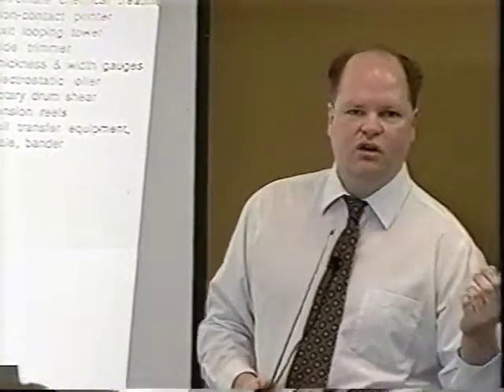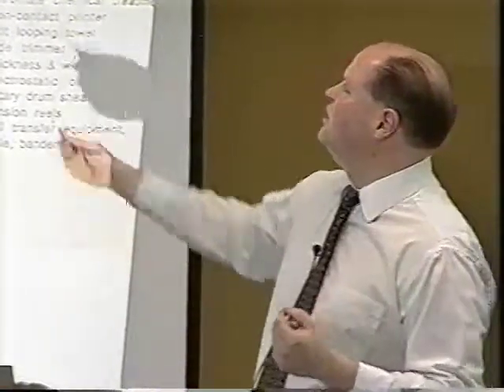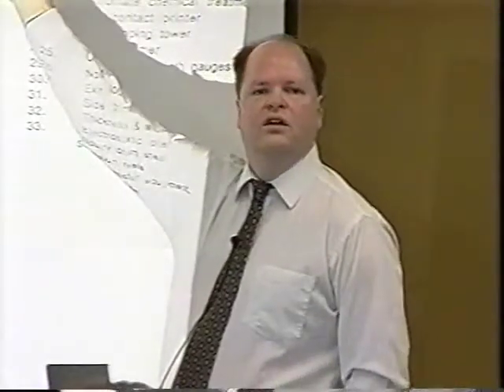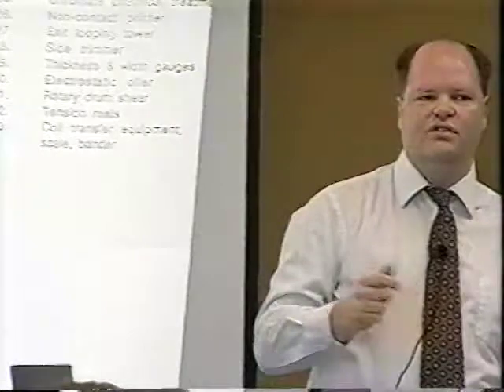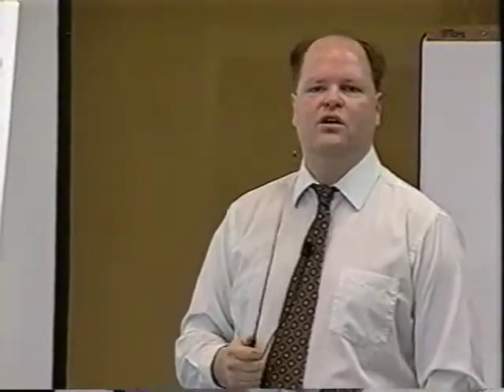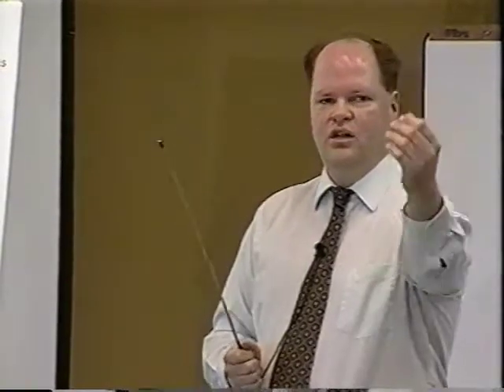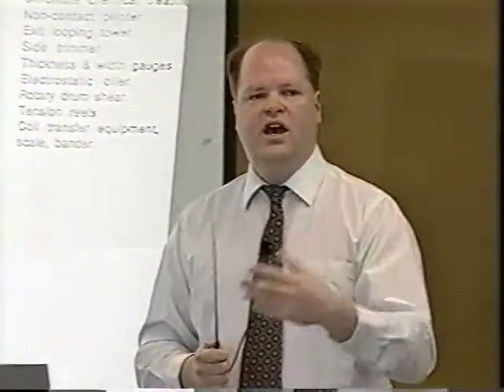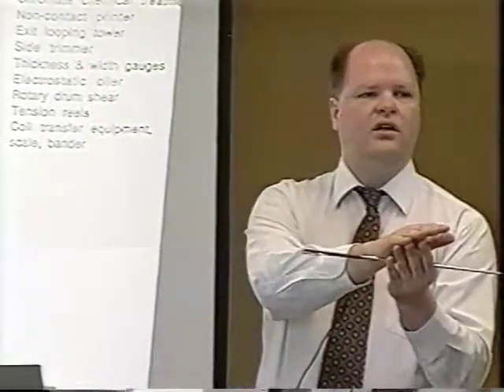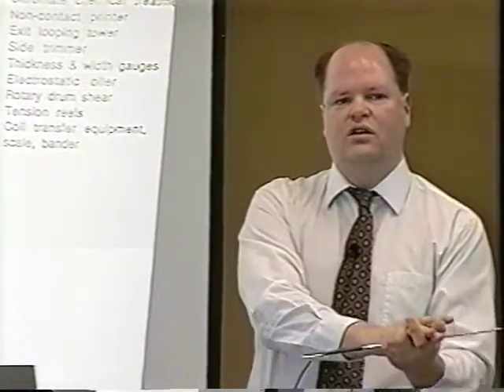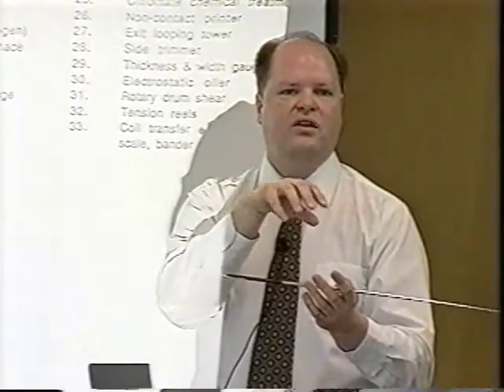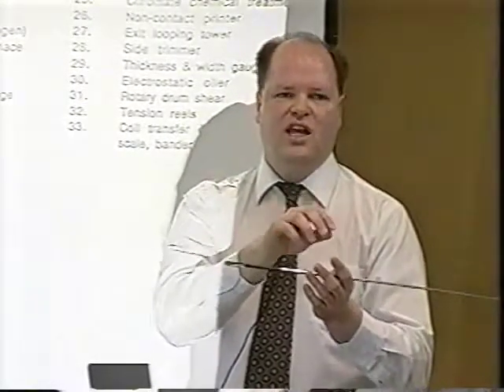The thing that does throw off galvanneal and makes it tricky is trying to measure the coating weight. Coating weights for zinc are very easy. You can buy X-ray gauges from any place in the country to measure zinc on steel. The problem with measuring galvanneal coating is that now you have iron in the coating and you have iron in the steel. So somehow the X-ray gauge has to know, when it gets a response from the iron and a different response from the zinc, did that come about because the coating weight's thinner and I'm picking up the steel, or is there more iron in the coating?